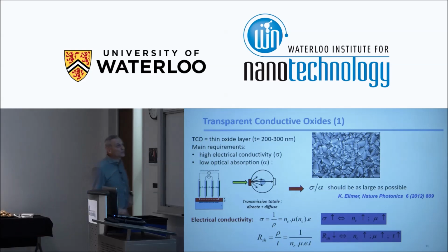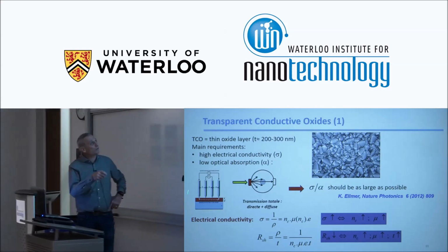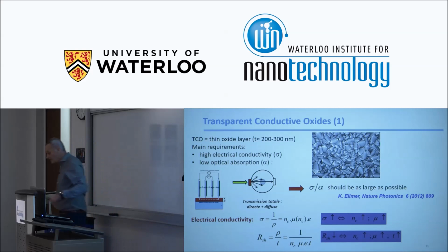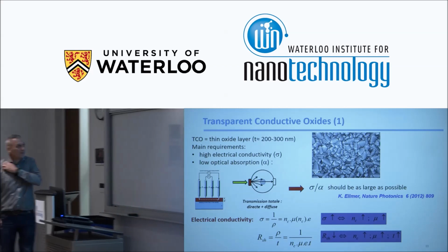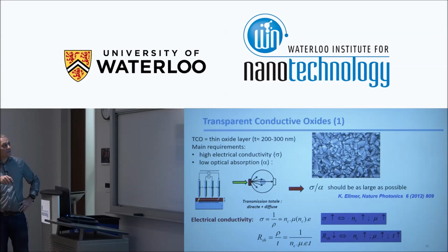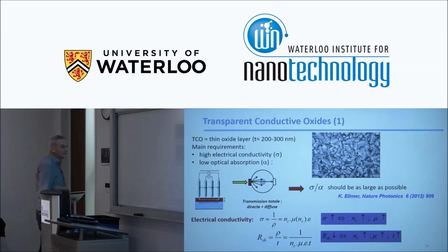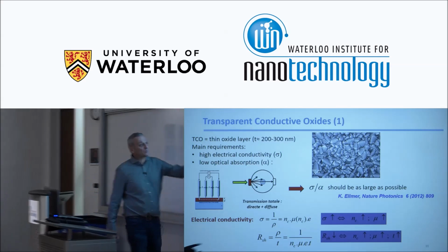And so we are for sure using, for example, a four-point probe to measure sheet resistance, and as well a spectrophotometer to measure the total transmittance or the haziness, for example. And the point is that if we want to optimize electrical conductivity, sigma, which is the inverse of the resistivity, this is directly equal to the carrier density times the mobility times the electron charge.